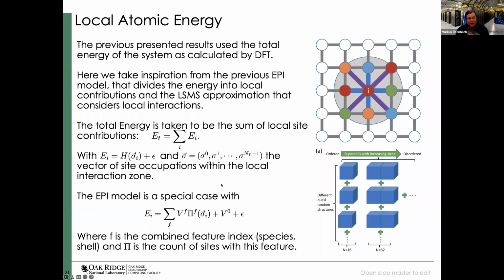Again, the idea for our energy model is sort of also inspired by the LSMS approach, where we have these local interaction zones. So we break up the systems into contribution from each of these local sites, and have an ansatz that takes the local contributions to the observables, to the observed energy.